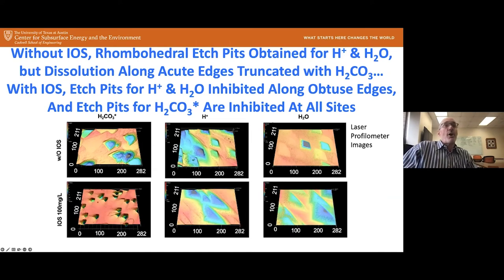Here we see that for the carbonic acid, we get very, very small etch pits formed, and then they're stopped. So basically, once we start forming them, the IOS is adsorbing, presumably, to these sites and then arresting the further development of these etch pits. And so that's why we decrease that, or at least slowing it down.